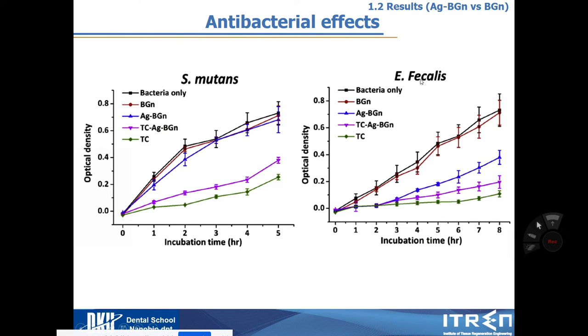But in the case of E. faecalis, when you look at this, they have more or less bacterial viability, which means that they have a bacteriostatic or bactericidal effect. We are not sure at the moment. And then after loading tetracycline, S. mutans and E. faecalis have very low bacterial viability. And when you use tetracycline as a positive control, they show like this. But this tetracycline amount is maybe 10 times more than in these. So we can say that this tetracycline-loaded AGBGN has some antibacterial effect on S. mutans and E. faecalis.